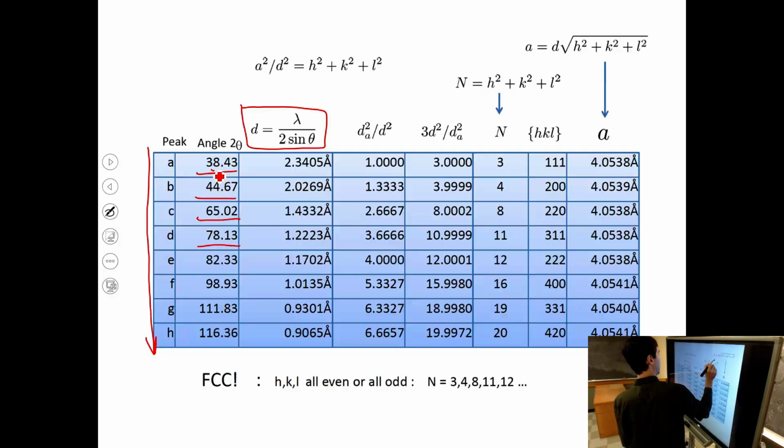And then we have a set of numbers like this, and okay, for convenience multiplied by 3. This is not the procedure that you have to follow for every set of lines. You just have to look at them and figure out which h squared plus k squared plus l squared this corresponds to. This is one procedure that they did in this example, but you can see that it corresponds to this pattern 3, 4, 8, 11, 12, 16 if you relate it to this formula.